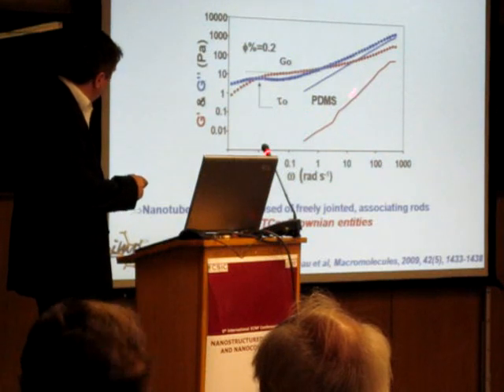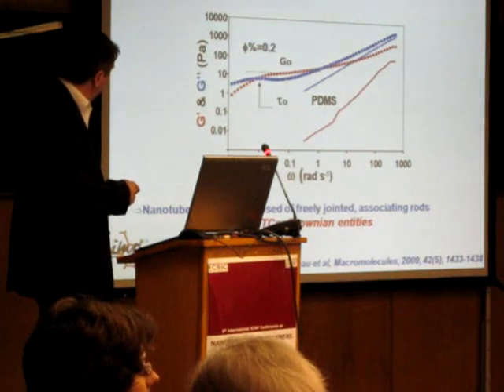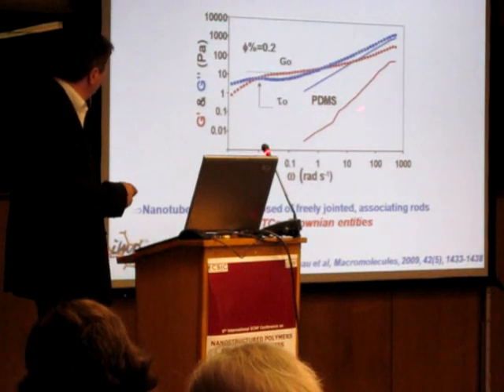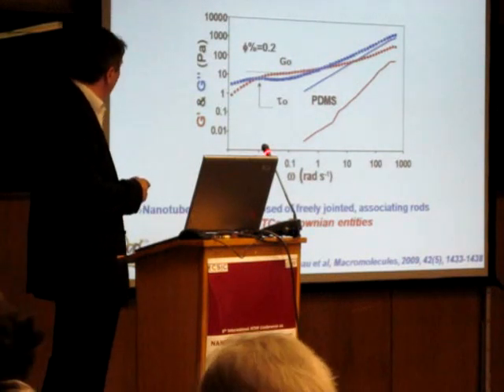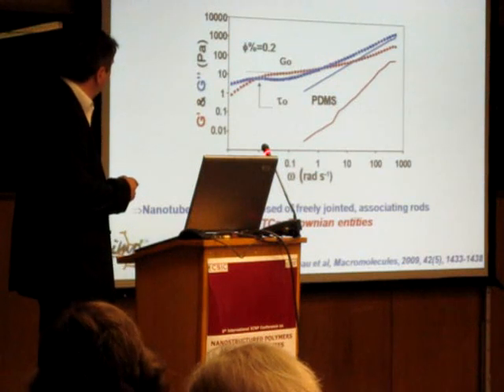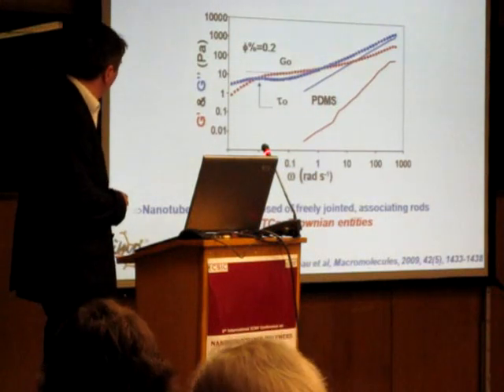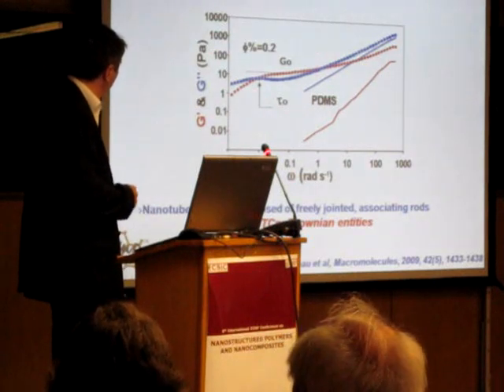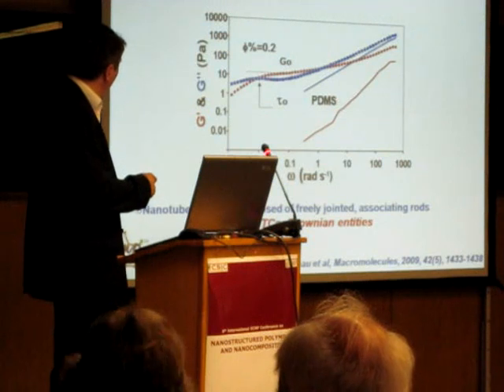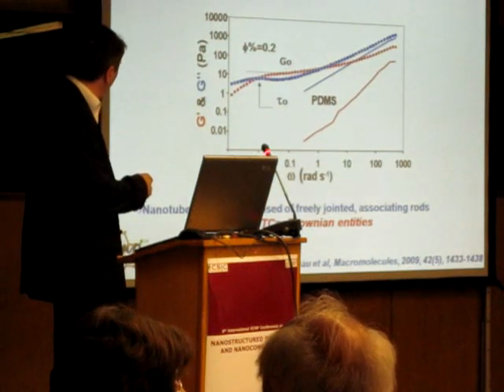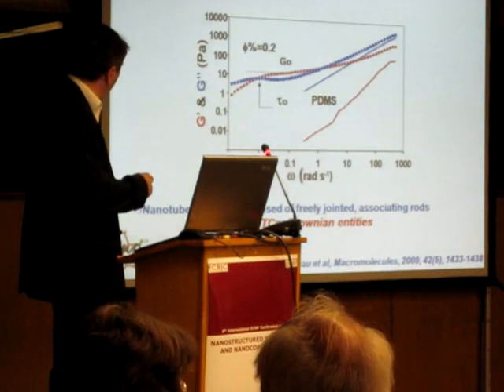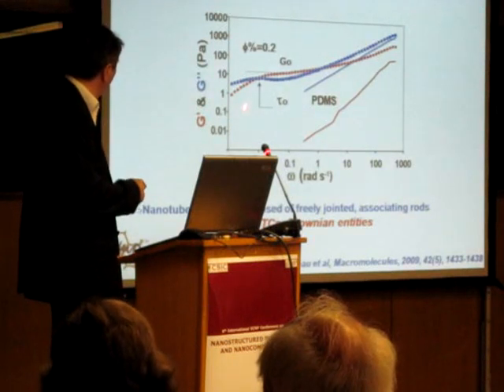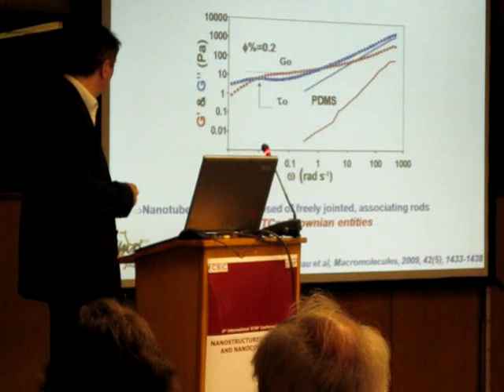And what is the result you see here? So this is the viscosity behavior of the matrix. And you can observe a strong variation of the viscosity property with only 0.2% of nanotube. And you have here the second relaxation zone with the second plateau modulus from which we can calculate the zero shear viscosity, plateau modulus and the relaxation time.